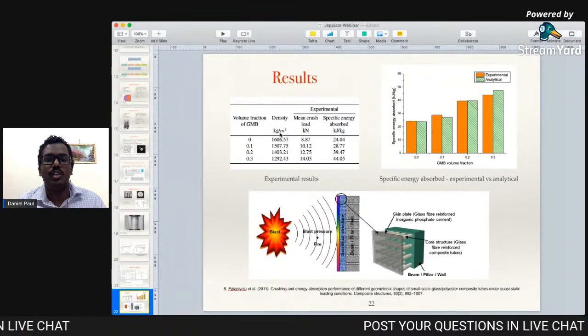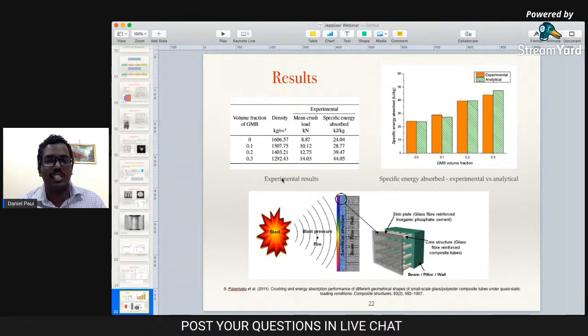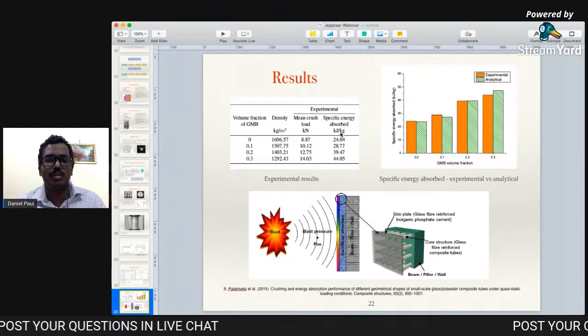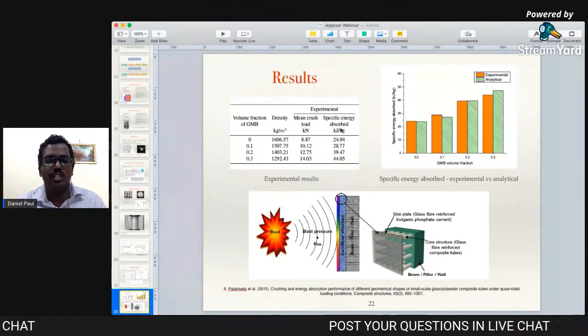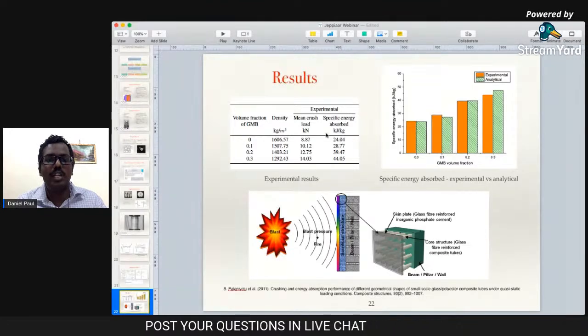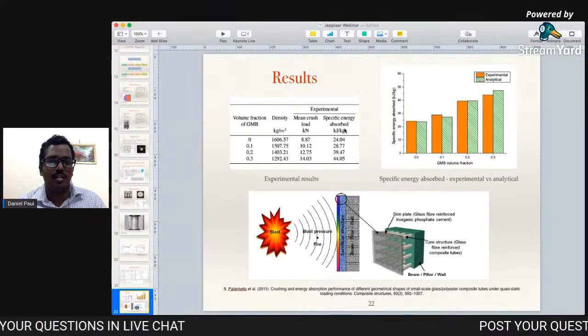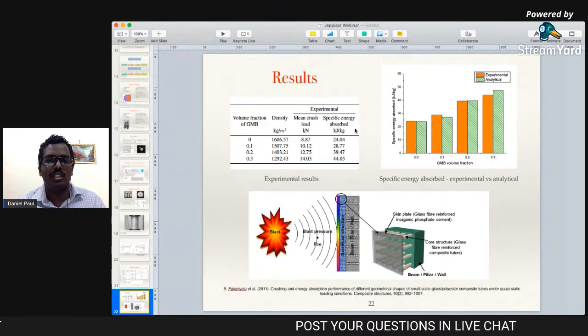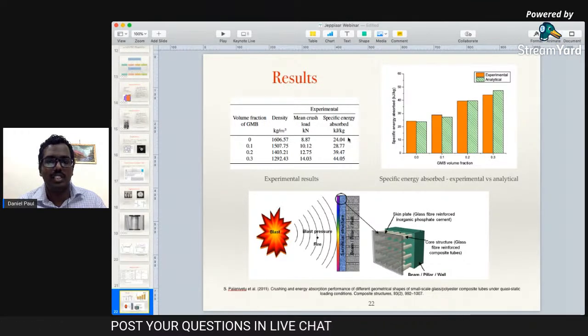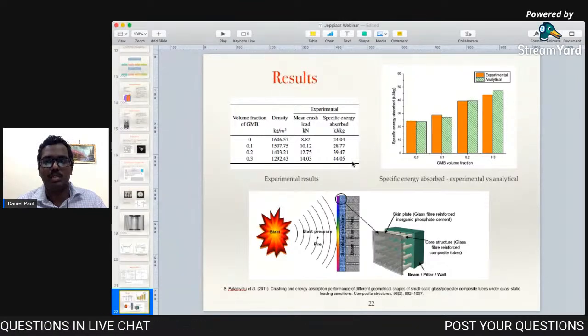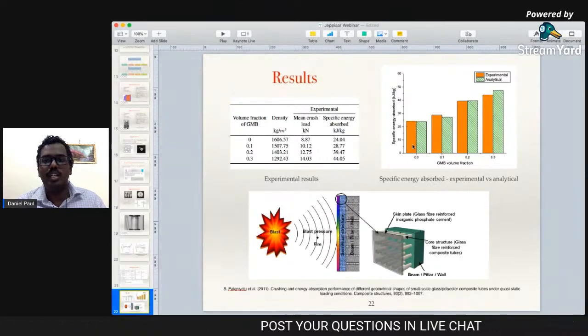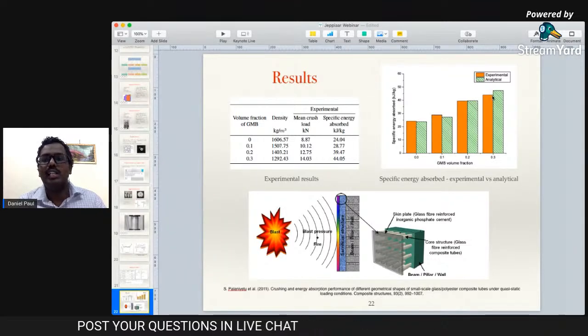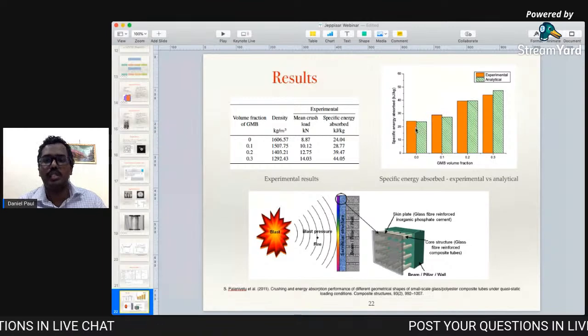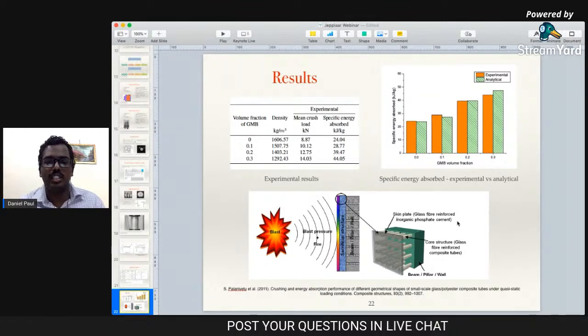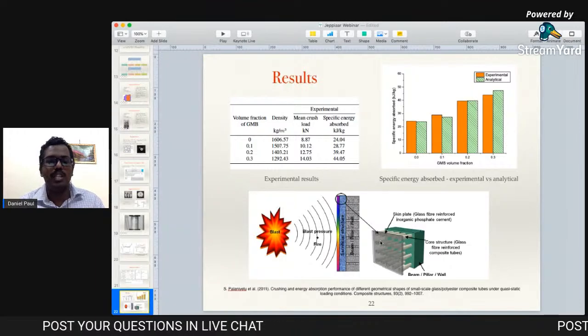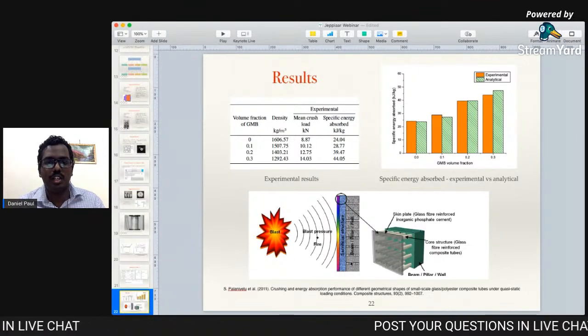Because these densities are different, to compare these materials of different densities, we have a term called specific energy absorbed. The specific property, as we saw, is the property itself divided by either the density or the weight of the structure. In this case, we have divided the energy absorbed by the weight of the structure, and we find an increase in the energy absorbed. When we see the experimental and analytical comparison, the analytical values are almost comparable to the experimental values.